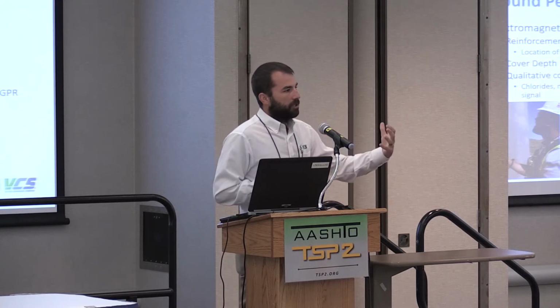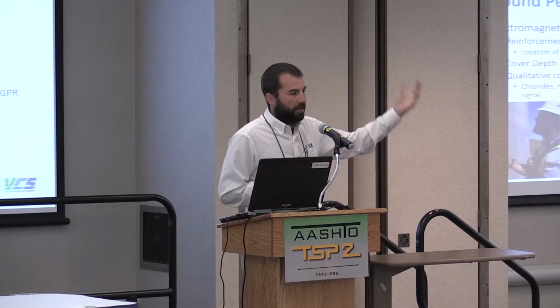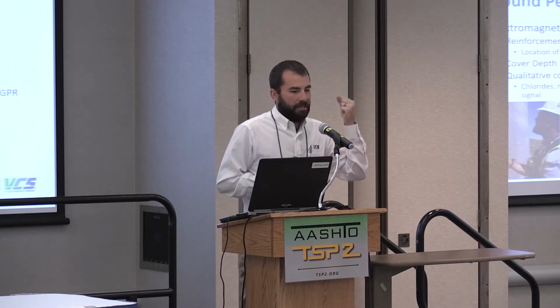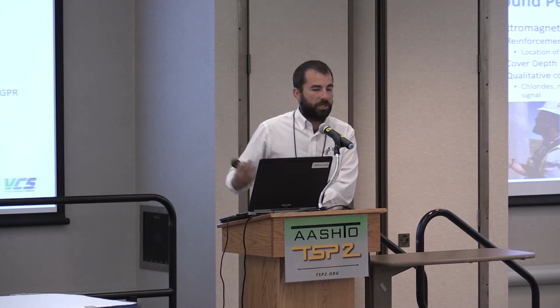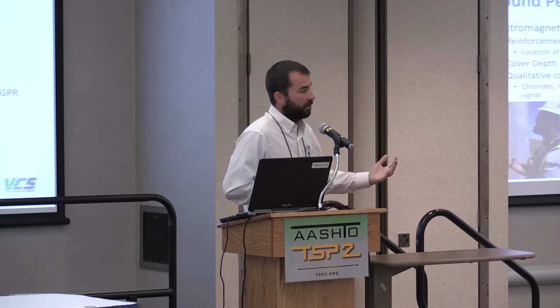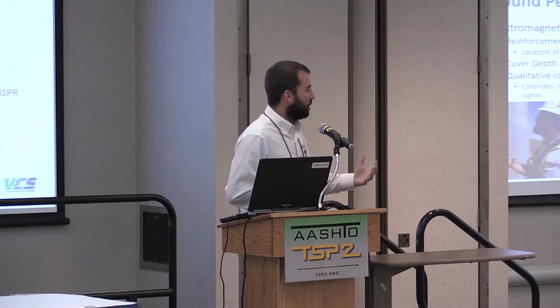A lot of people like to use GPR and say, oh, I'm going to go out and do a delamination survey, or I'm going to go out and find you section loss. Well, GPR is good because it's affected by so many things, but I can't tell you if this area is delaminated, or maybe there was just a lot of moisture exposure there. Maybe it's near a drainage path. Now, that might lead to a lot of deterioration in the future, but that doesn't mean there's deterioration today. Using GPR as a tool for further investigation, I think, is really useful, but you have to understand and qualify that information and make sure you're not stretching it too far.